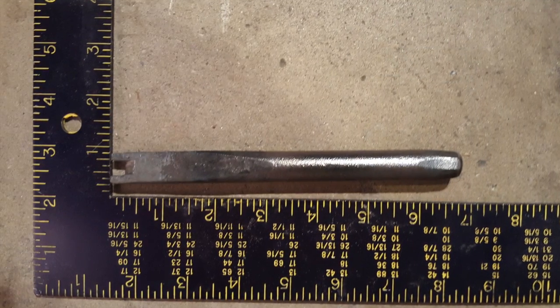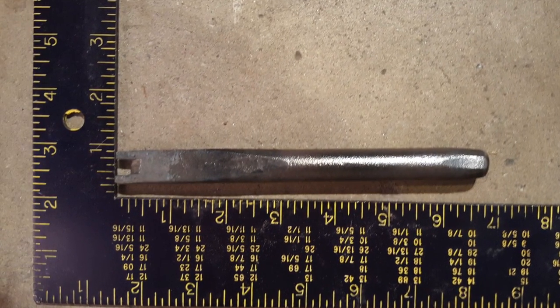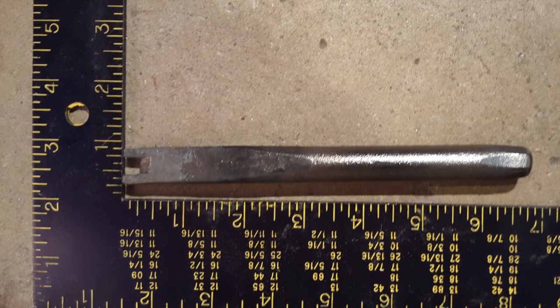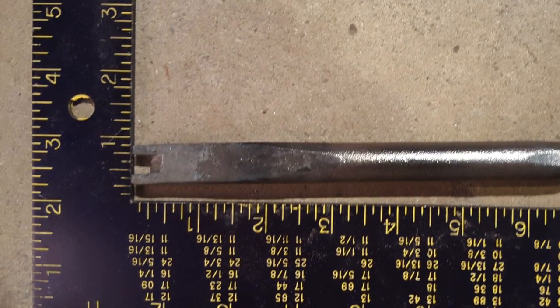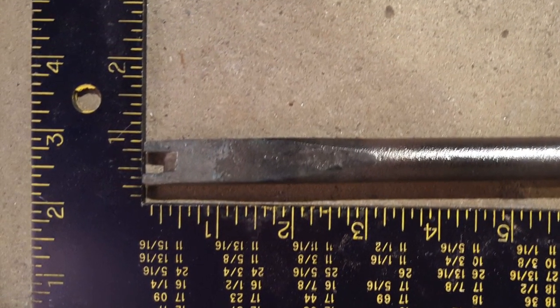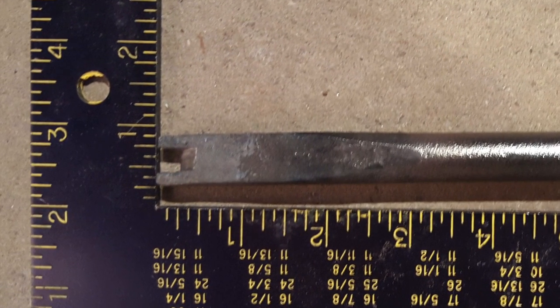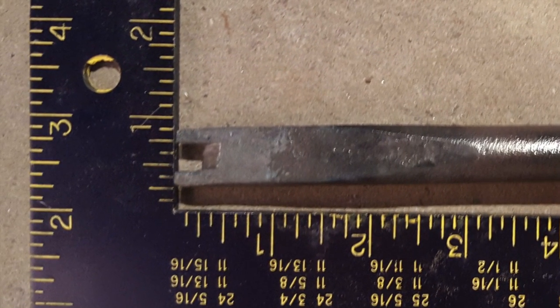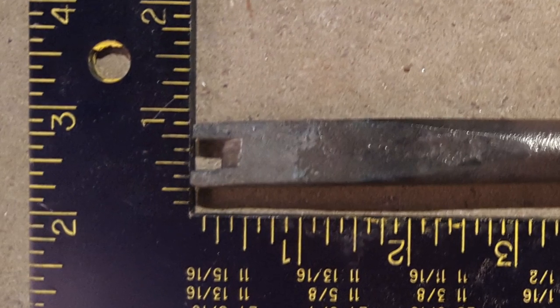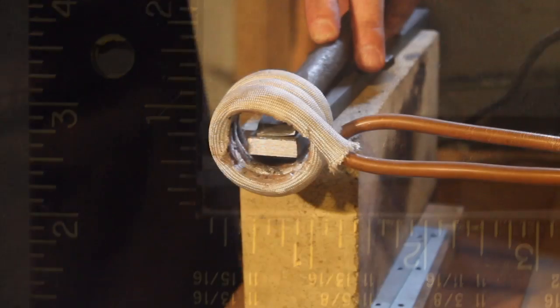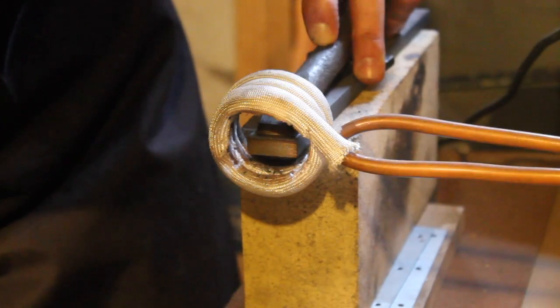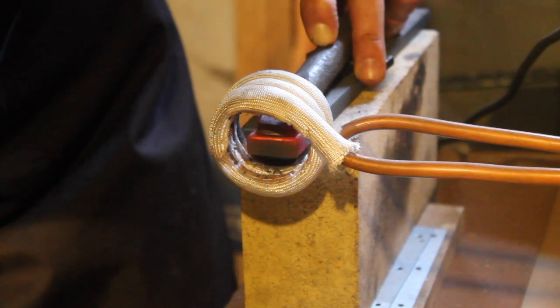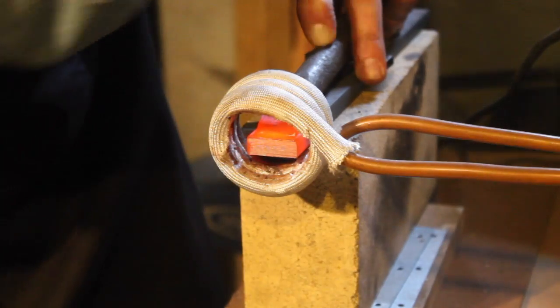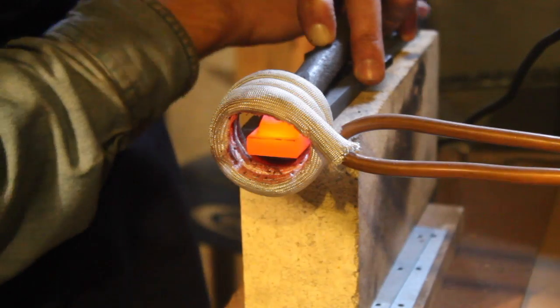Heat treating an edge tool is surprisingly tricky. The small thin edge doesn't get as much heat as the larger mass behind it, yet it has significantly more surface to radiate heat away. I found that I had to get most of the end of this butcher to an orange heat just to get the edge to cherry red. To deal with this problem, I've placed this butcher against a piece of 3/8 inch by 1 inch flat stock. This provides heat and effectively insulates on one side.